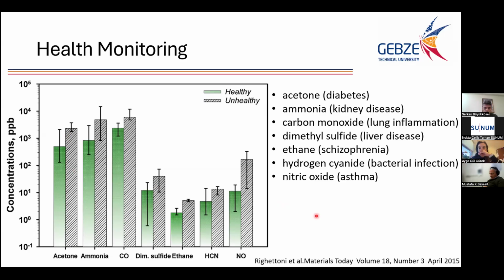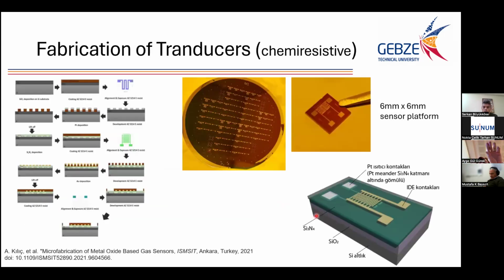Okay. Now let's look at how we fabricate our sensors. As I said, sensors are composed of both transducers and the sensing material. Now I'm talking about the fabrication of transducers. For the fabrication of transducers, we use microfabrication methods. For the details, you can check the reference here. Basically, we use 3 lithography steps, and at the end, we get 6 mm by 6 mm chips. It's a silicon substrate with silicon oxide on top and silicon nitride between the platinum heater and gold electrodes for chemical and electrical isolation.